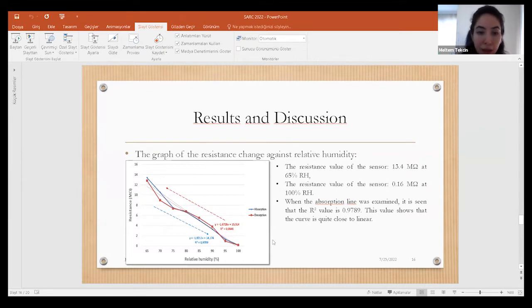For the absorption line, the resistance value of the sensor was measured as 13.4 megaohm at 65%, and the resistance value of the sensor was measured as 0.16 megaohm at 100% relative humidity. When the absorption line was examined, it is seen that the R-squared value is 0.97. This value shows that the curve is quite close to linear.